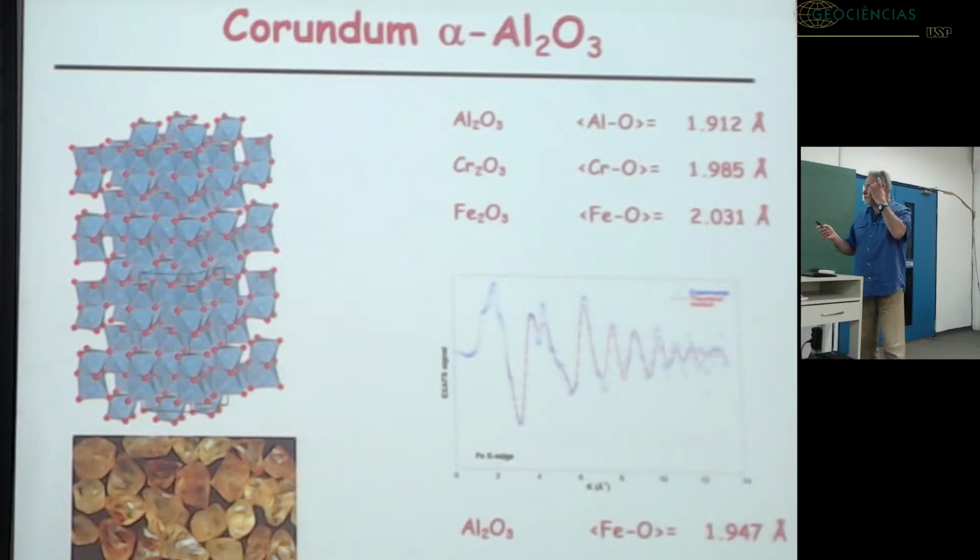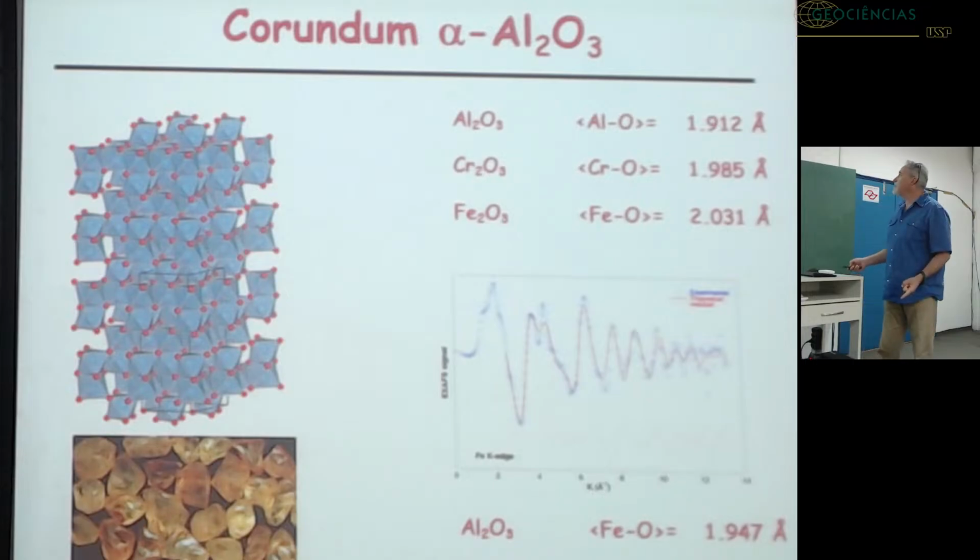In the case of the corundum structure, we have a hexagonal close packing of oxygens. So if you try to enlarge one of the octahedra, you have to strongly modify the size of at least 6, if not 12, neighboring octahedra. In this case, the structure does not relax around the dopant. So basically, the structure says to the dopant, if you want to enter, you have to take the space we let you have, with no possibility to strongly, locally distort the structure.